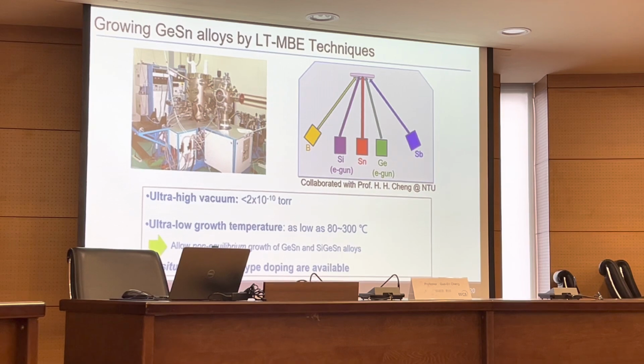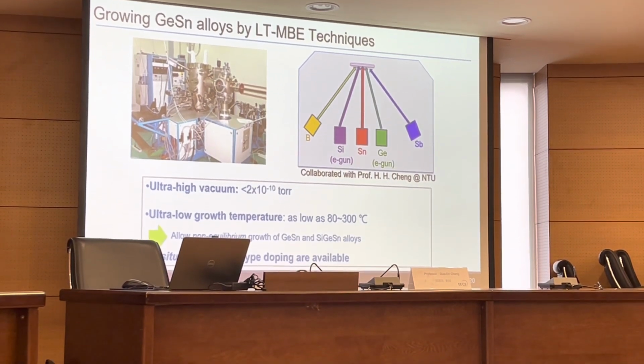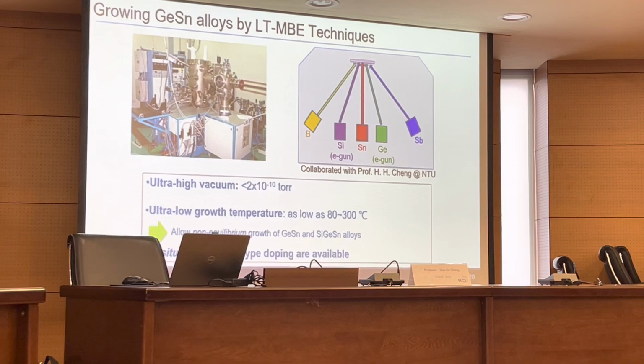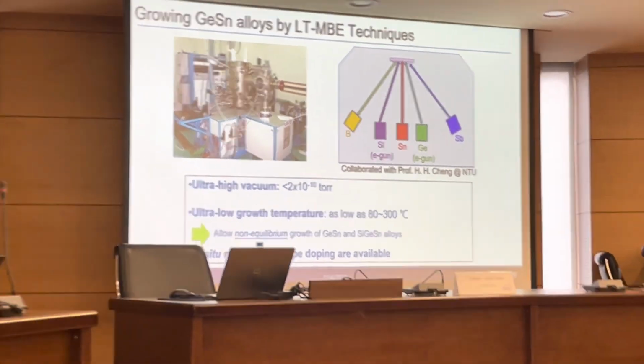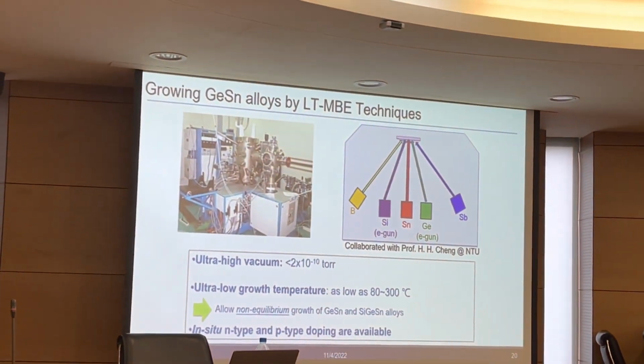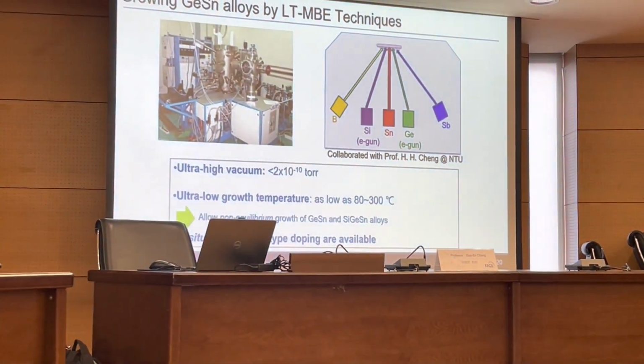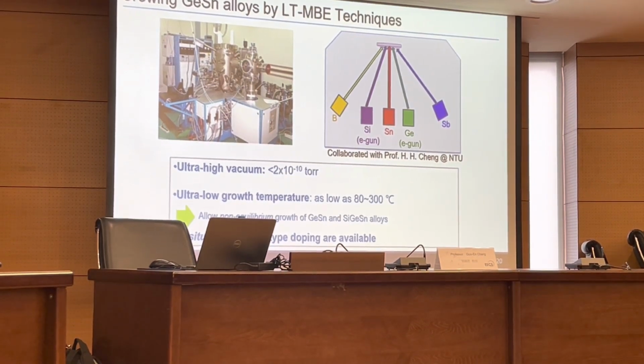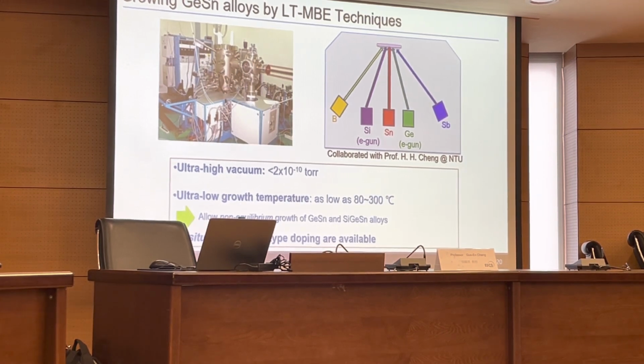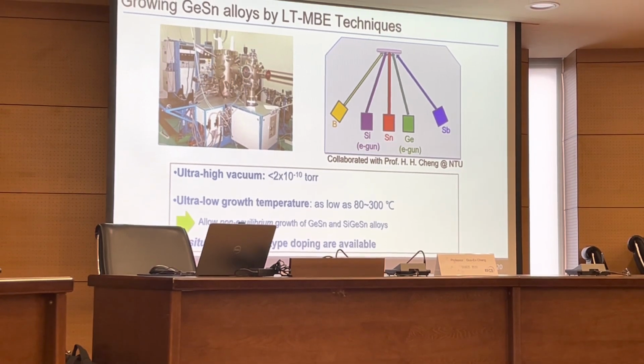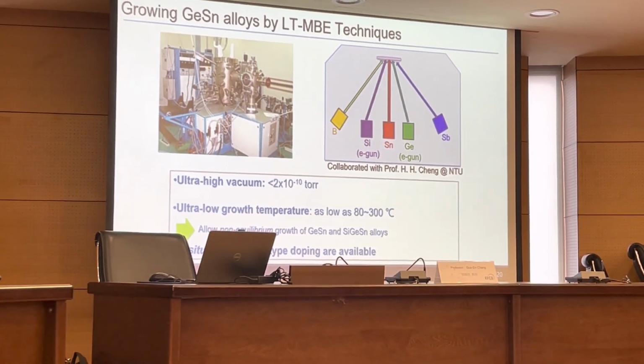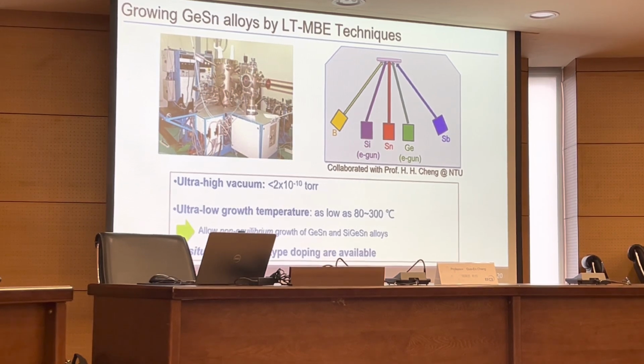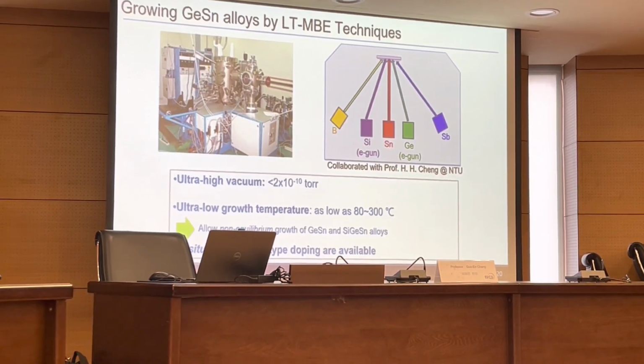So how do we try to address this challenge? The first thing is we grow a germanium tin layer using molecular beam epitaxy at a very low temperature. Because, as I just said, in thermal equilibrium state, tin atoms tend to run away from germanium, we are trying to grow it using non-equilibrium conditions to achieve high tin content.